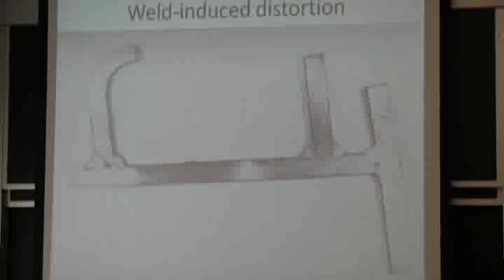The reason I'm bringing it in is, if you look at that distortion, what happened is they did have a groove, like we talked about here. This was a type of 45-degree groove on the T-connection. So it wasn't on a flat, but they ground off one side, and that's why they're able to make the weld bead penetrate into the piece that far. But then when it solidifies, it shrinks and bends over. That's why this piece is tilted towards our left-hand side, because that's the first bead that came in. It's a bigger bead, so when the one on the other side came in, it didn't do a thing. So you end up with this distortion.